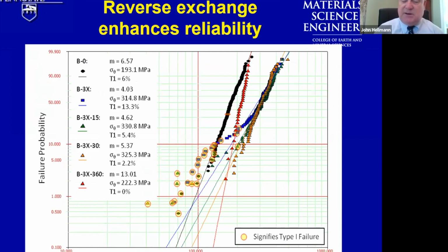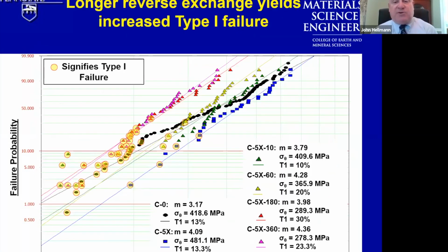glass articles. Furthermore, longer reverse ion exchange processes yielded increased occurrence of type 1 failure. Type 1 failure is the failure of the proppant particle into large chunks, not fine particulates. Type 1 failure is desirable for their application as proppants. We verified that this failure process was indeed occurring using interrupted load tests.